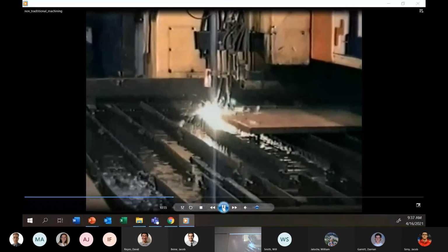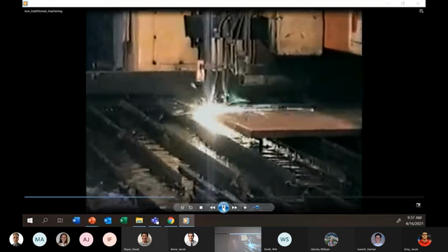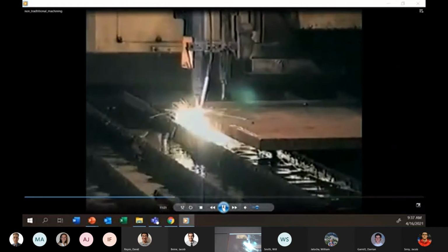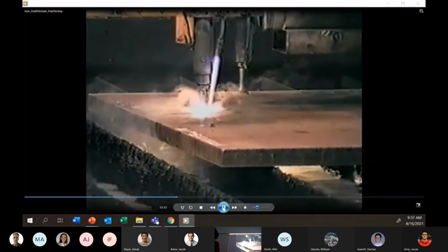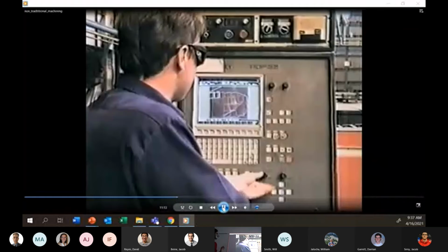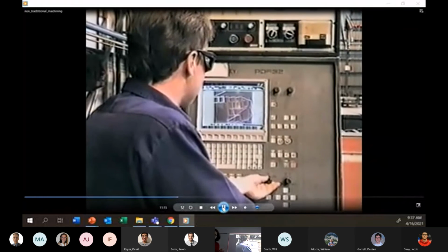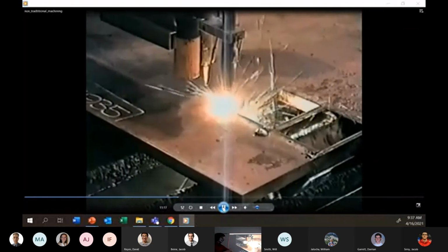For plates of greater than 30 millimeters thickness, the feed rate for plasma arc and oxyacetylene cutting is similar, but there is a cost advantage in favor of oxyacetylene. As plate thickness increases, so does this advantage. However, this process requires a higher operator's skill to achieve a first-class result.